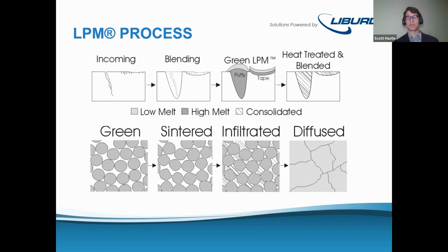Before we talk about what happens after being heat treated and blended, I'm going to go into what happens at this arrow here within the deposit. Down here, you'll see the green areas. These are just balls of super alloy. As they're brought up to temperature during the consolidation heat treatment, they actually get partially sintered together, and it's going to form a bit of a lattice between those balls of super alloy, and that gives it a little bit of strength as it goes up to the higher temperatures.